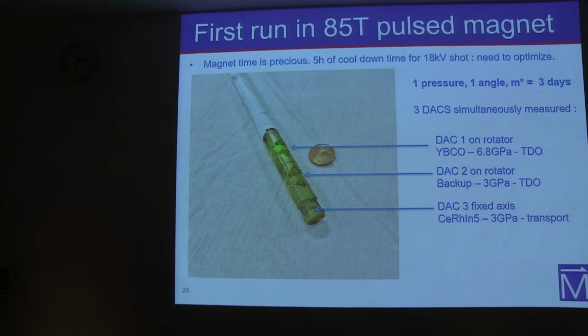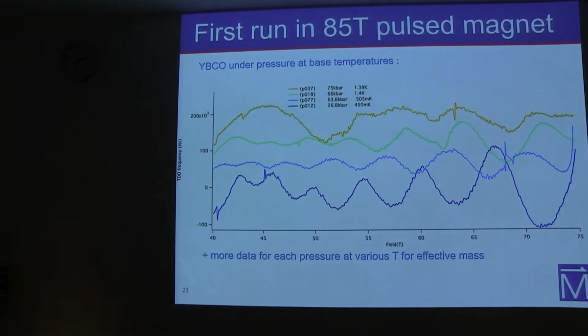So this is a picture of the probe that we developed and rebuilt in Dresden, and we can actually see 3 pressure cells here. One on top here on the rotator to rotate in field with the laser to measure the pressure. A second one here also on the rotator, and the third one here on the fixed axis. So we can do 3 simultaneous high pressure measurements in pulse field. And those are our initial data in 85 Tesla magnets, so here up to 75 Tesla. And we went as high as 75 kilobar. It's really difficult to make those pressure cells go to higher pressures.